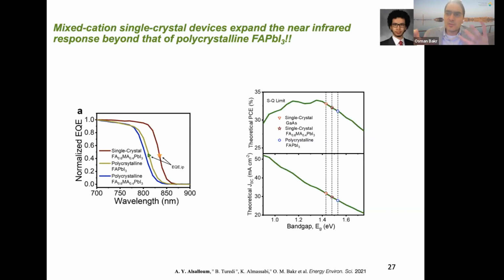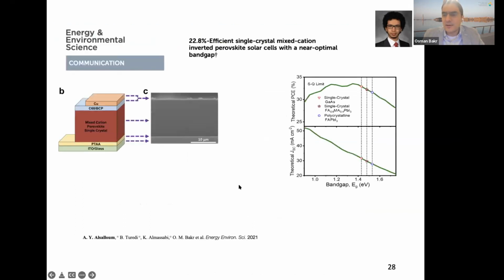So we started mixing methyl ammonium and formamidinium ions to try to shift the band gap. And what surprised us is that single crystals have a band gap that, when you mix methyl ammonium and formamidinium, is narrower than pure formamidinium by itself. And so based on band gap engineering and shifting the band gap, we were able to push the devices even further, closer to the 23% mark. And for inverted type solar cells, this is close. At the time, this was almost a record for these types of solar cells.